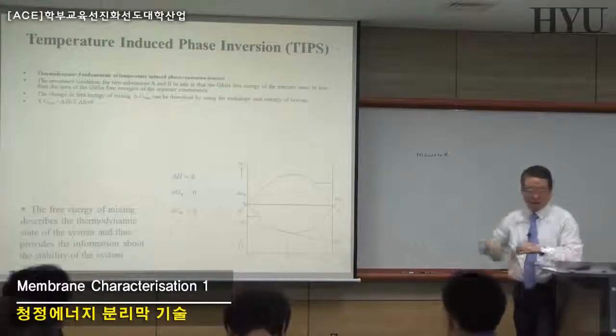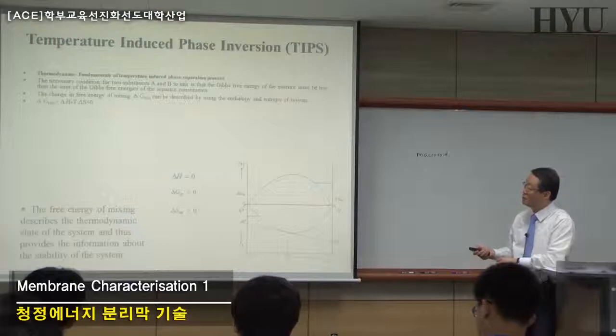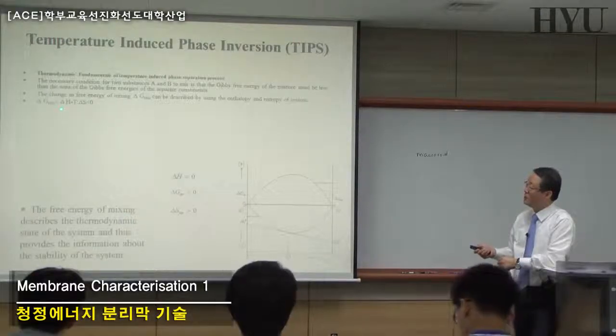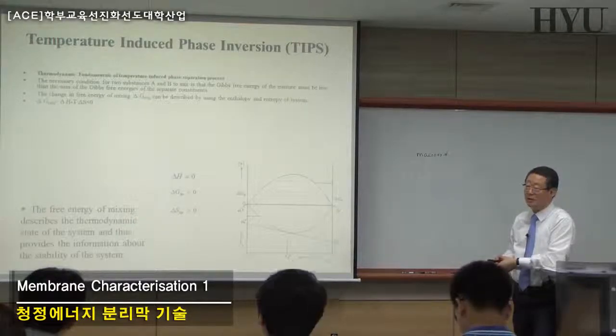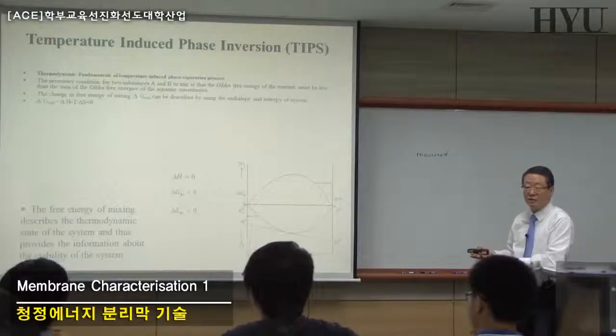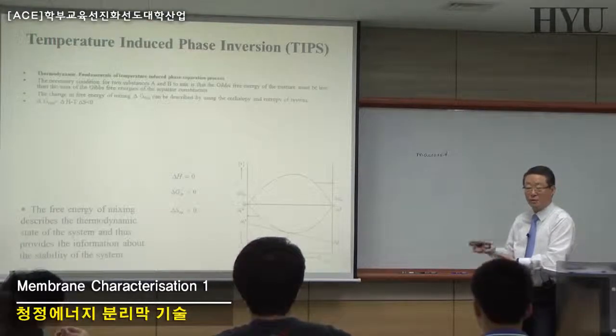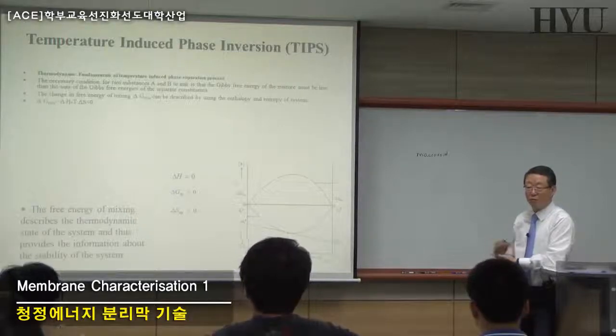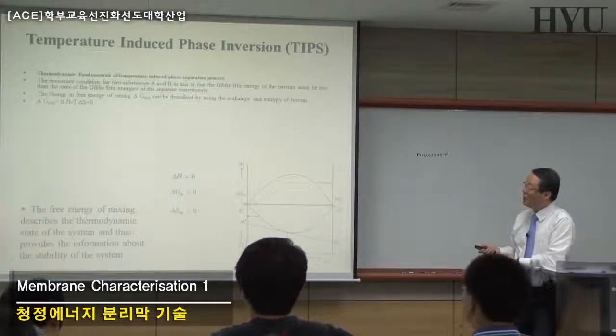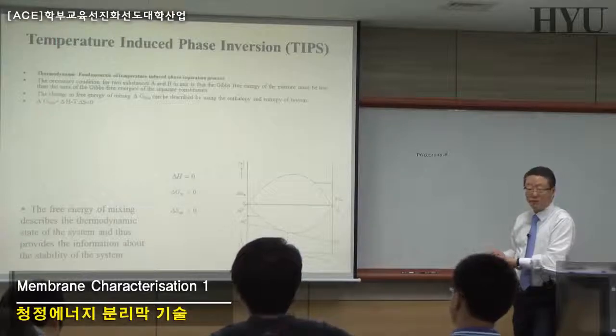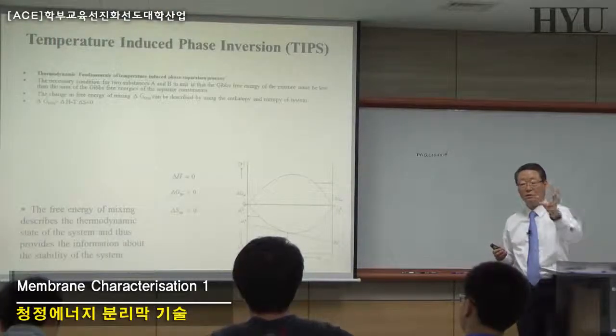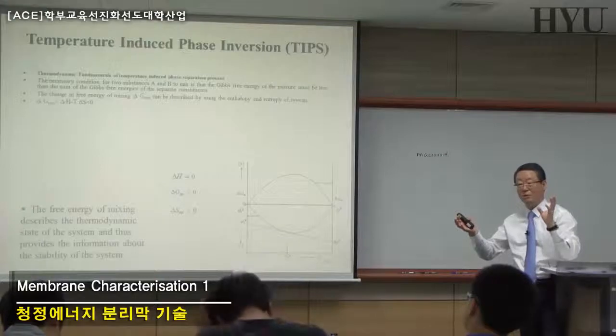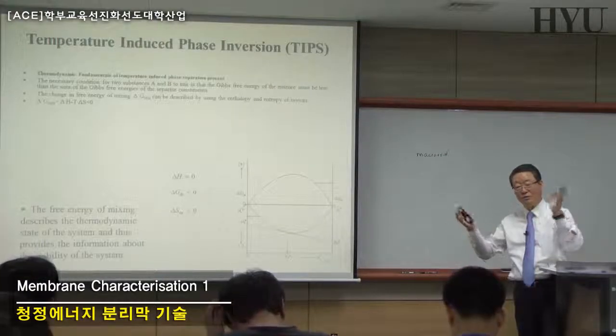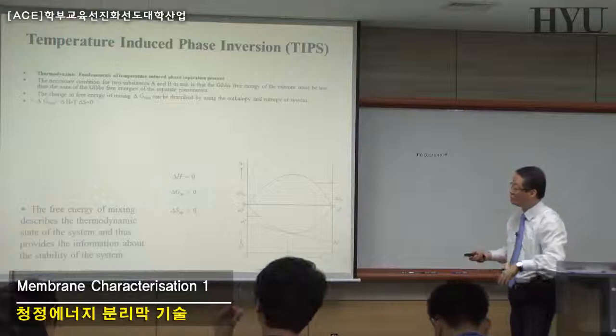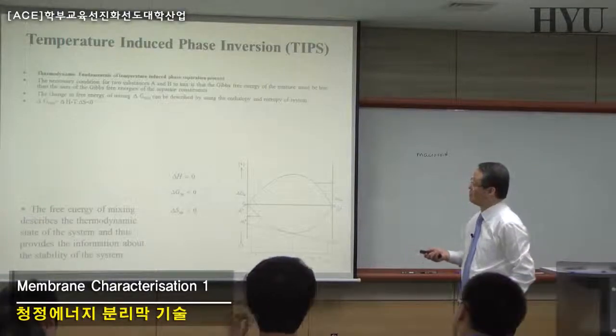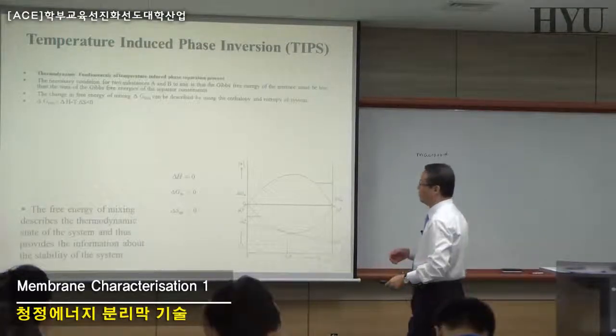Well, thermodynamic factor, for example, the Gibbs free energy of mixing can be defined as delta H minus T delta S, and it should be always negative in order for your polymer solution to be mixed to form your polymer membrane. Okay? Now this is the Gibbs free energy difference between the first phase and the second phase. So the Gibbs free energy of mixing should be always negative.